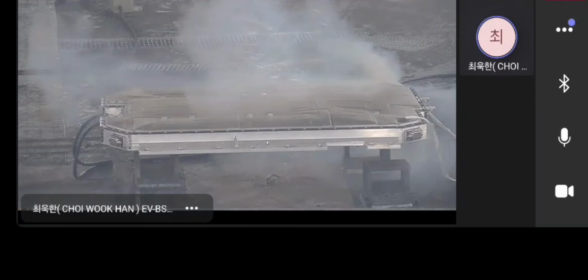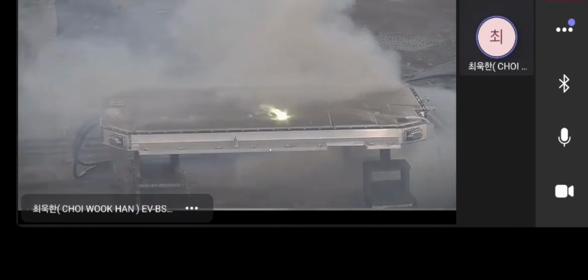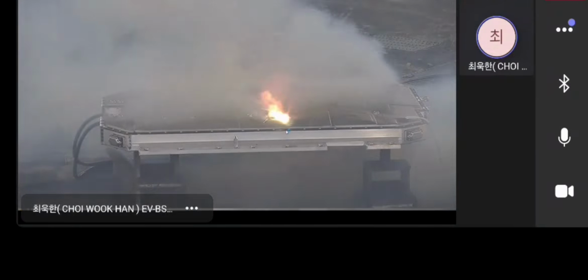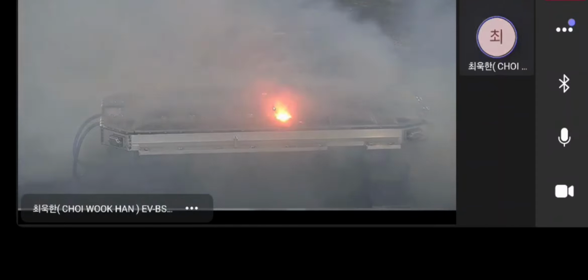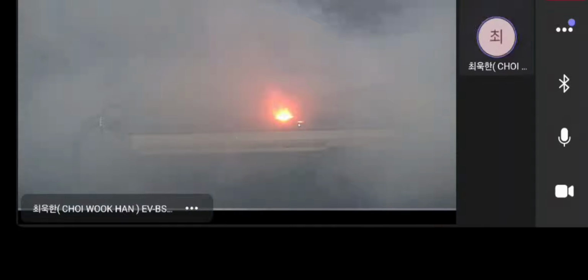Here you can see the thermal runaway test using one of our existing zinc flake products. It passed the torch and grit test, but in the full thermal runaway test, it ignited. This was the turning point. Even within zinc flake coatings, conventional products could not survive the most severe conditions.